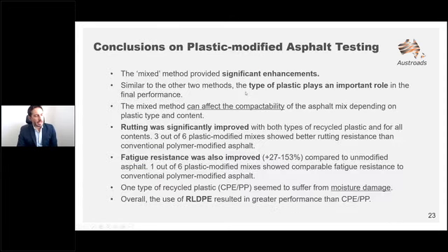So, concluding the asphalt assessment, you will find many more data sets in the full report. You will find resilient modulus, cracking tolerance, and many other parameters there. But to keep it within the 60 minutes, we have to cut something down. Concluding on this part, the mix method provided significant enhancements, much more than the other two methodologies. The type of plastic obviously is important. I showed you the difference between RLDPE and the commingled version of PEPP.